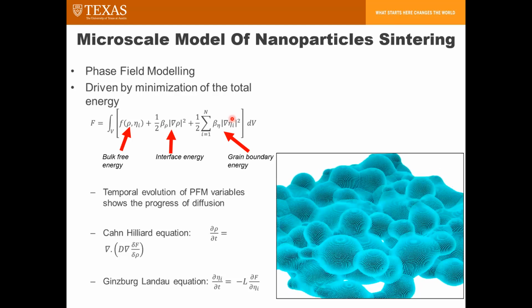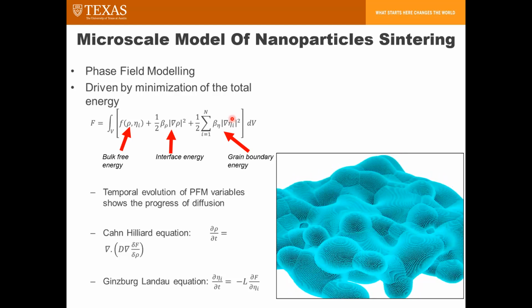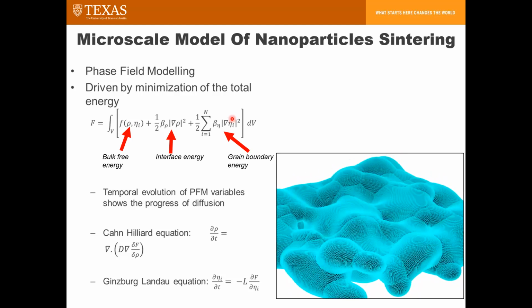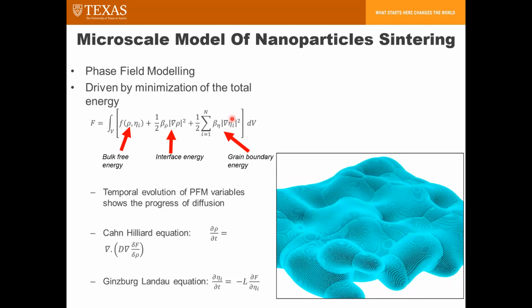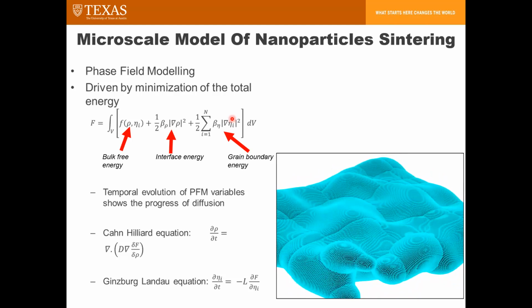So this slide shows a video of the simulation applied to a 2x2 micrometer bed. What we can see in this video is that we have initial stages of rapid neck formation between the particles, and then the necks grow and we see densification and shrinkage. So the evolving particle configurations from beds such as these are passed into thermal simulations to calculate the thermal conductivity of the powder bed.